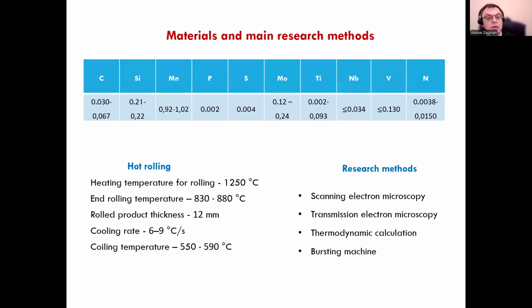Low-carbon steels with different combinations of microalloying elements from the general titanium, niobium, vanadium, molybdenum system produced under laboratory conditions were studied. The steels were smelted in a vacuum induction furnace with a magnesia crucible. The chemical composition of the investigated steels is presented in the table.